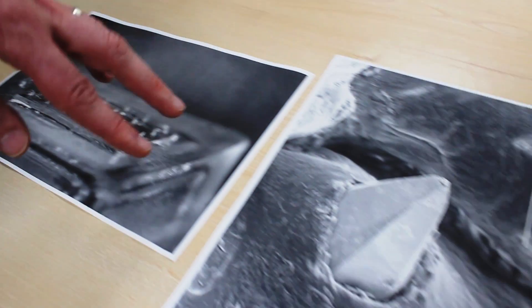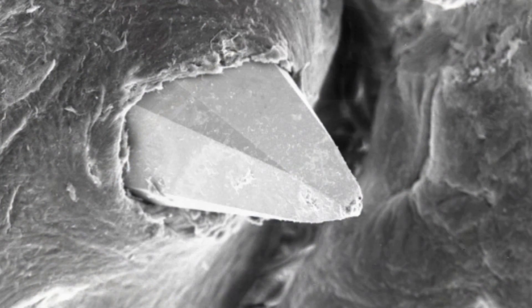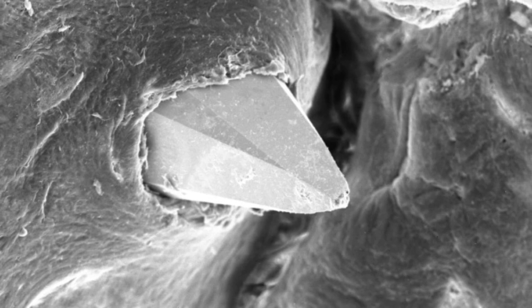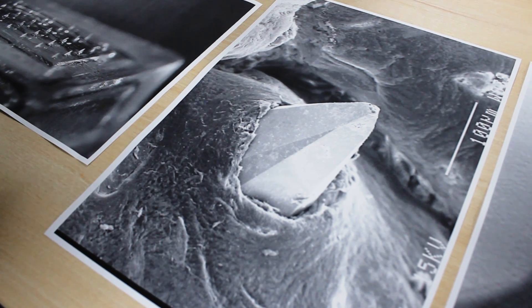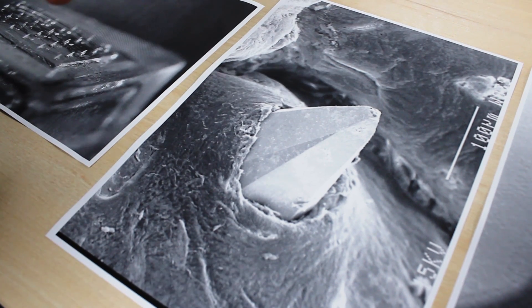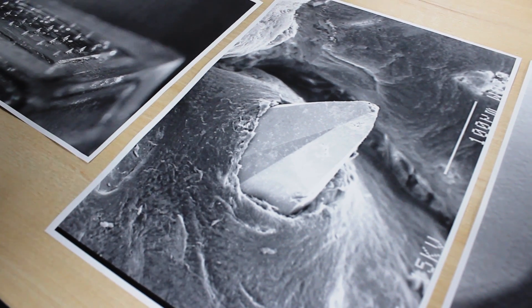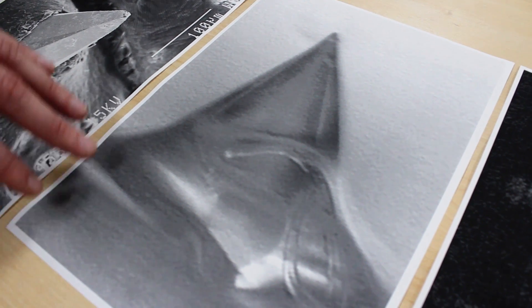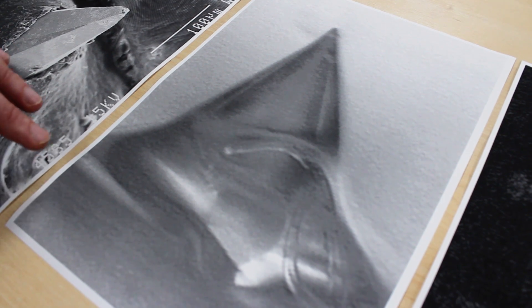Our next image shows a scanning electron micrograph of a single microneedle penetrating through the stratum corneum, which is the outermost barrier layer of our skin. Once our microneedles are in skin, they will rapidly take up skin interstitial fluid to form these discrete hydrogel bulbs, and that's what we see in our next image. Even though our microneedles become soft when inserted into skin through uptake of fluid, we can see here a microneedle that has been removed from skin completely intact, with no polymeric material deposited behind in the skin.